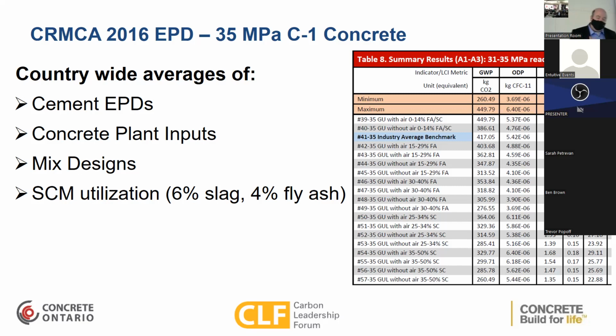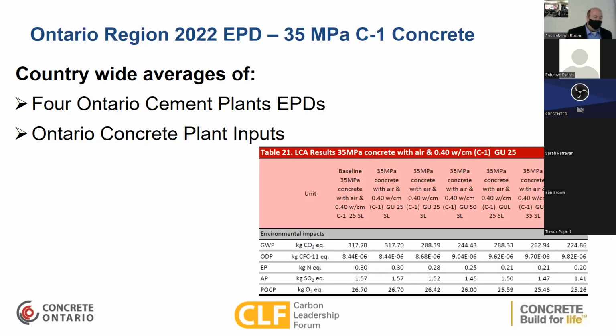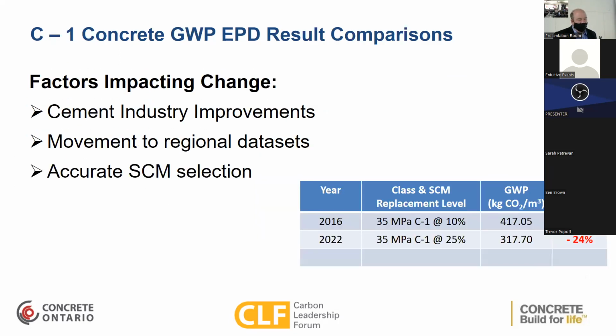So we've decided to tackle it a little more properly this time around, and we've broken that data down by region. So it makes more sense and it gives you a better handle on what the actual carbon intensity is. So if I look at our 2022 data, 35 MPa C1 concrete, we have 4 Ontario cement plants averaged into the EPD. We've got just Ontario concrete plant data, and we've got just Ontario mix design data. So again, we're trying to give you more accurate information.